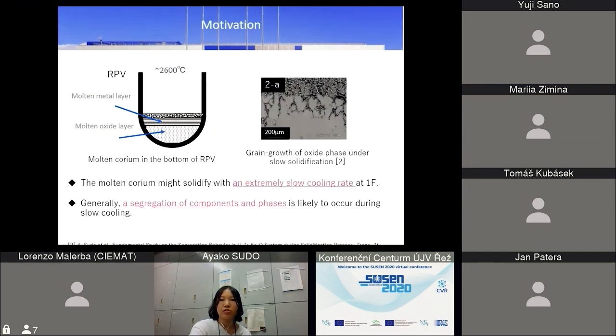Okay, next is motivation of our work. The molten corium in the bottom of the RPV at 1F might solidify with a slow cooling rate. Generally, a segregation of components and phases is likely to occur during slow solidification. This is the same image of the grain growth of specific oxide phase under slow solidification. This heating test was performed in laboratory scale, and under such slow solidification, such grain growth of specific oxide phase or segregation of components is likely to occur.